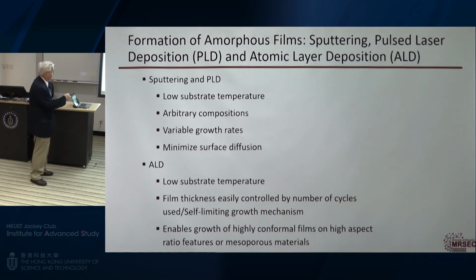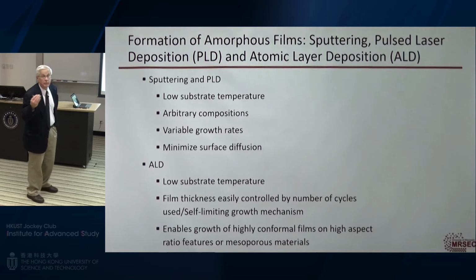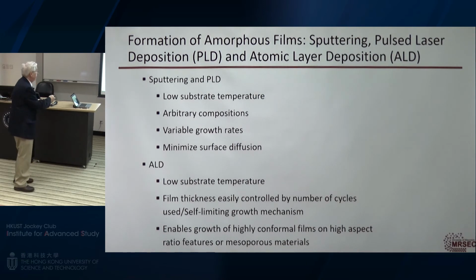So the trick is, by going from an amorphous material to a solid epitaxial material, I can use the limited mobility in the solid phase to create the epitaxial order. And so we can do that by sputtering. You can do this by atomic layer deposition as well. What's nice about atomic layer deposition is that it's very conformal in the sense that it can get into very small spaces. And so I can make amorphous films that have very, very unusual geometries to them.